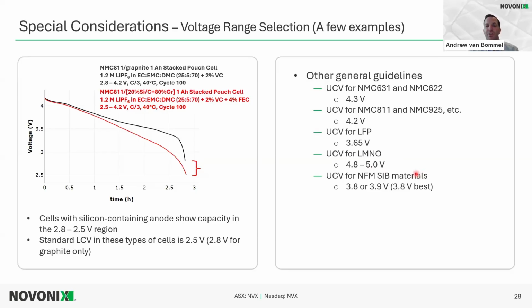For sodium-ion battery materials, one example is the layered oxide containing nickel, iron, manganese, like the 111 sodium nickel iron manganese oxide. Those materials cycle best at 3.8, so they can be cycled at upper cutoff voltage 3.8, 3.9. Some of the newer ones may be able to cycle to 4.0, and they're getting better as more development is made. But if you want good cycling of those materials, you get much longer cycling at 3.8 volts.